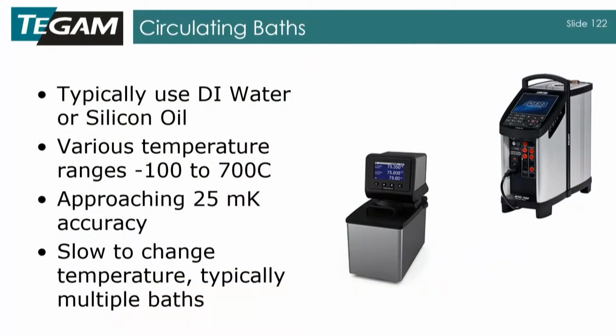And what happened is the water affected the encapsulant on the RTD that we were using. So the RTD now is changing. Every time we used it, we couldn't come up with consistent results with the RTD. So we actually had to go to a silicon oil for that. So we found some interaction between the bath medium and the sensor itself that we were trying to calibrate. That was, like I said, developing the calibration system for the product was harder than developing the product.